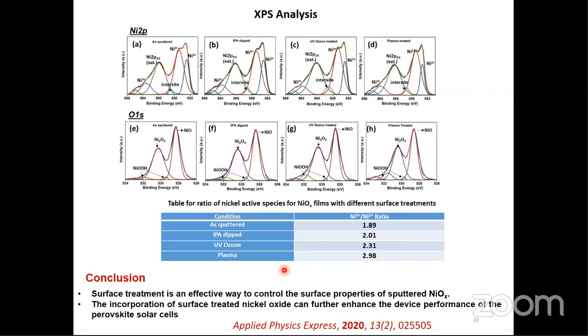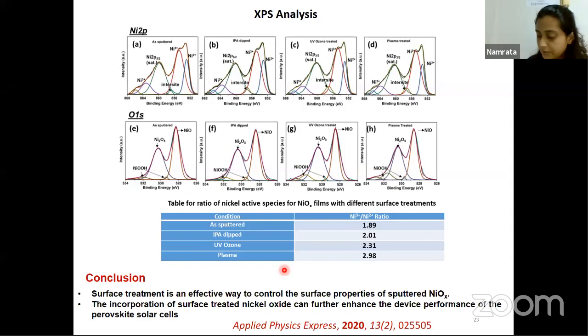How can lifetime be calculated from the log intensity versus time plot from the time-resolved fluorescence spectroscopy? Okay, we have an equation for that. We take the TRPL data and we fit it with a bi-exponential law. Maybe I cannot recall the entire equation, but you should check it. We can calculate the lifetime from there.